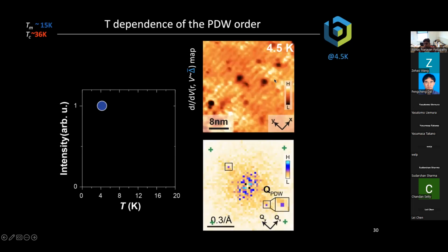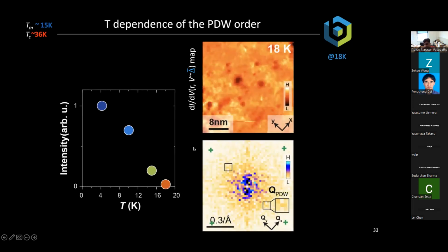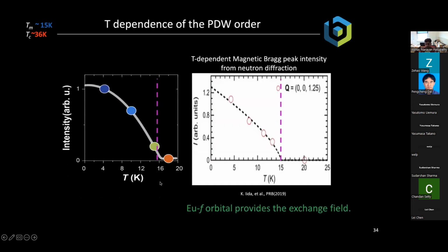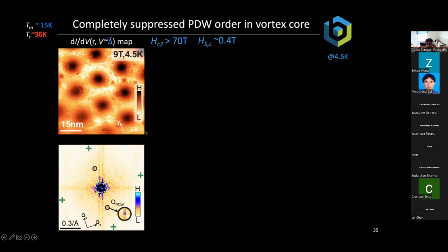And I hope all of you see that when we go across the magnetic transition temperature, this phenomenon is gone. So this phenomenon really depends on the presence of the magnetism of the europium in order to exist. And if you look at the intensity of how these features die away as a function of temperature, this is similar to how magnetism itself in the material dies away as a function of temperature. So this is how the magnetism disappears from neutron diffraction. There's some similarity between how the magnetism disappears in intensity and our features disappear in STM.